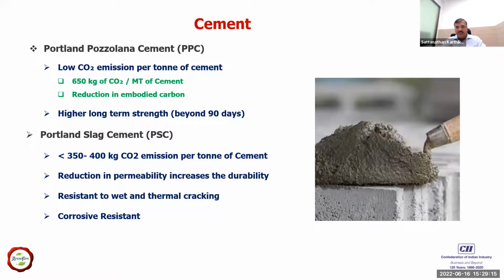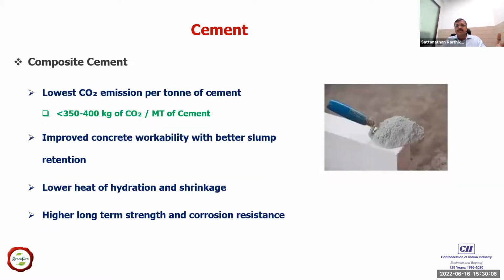Very similarly, there are other options available. For Portland slag cement, the slag can be added to the extent of about 70% as per the BIS standard, so obviously the carbon footprint comes down even lower. Compared to OPC, there is an increase in durability, and it also addresses corrosion-related issues. Even in terms of thermal cracking, it is a much better cement compared to ordinary Portland cement. So apart from the reduction in carbon footprint, if you go for blended cement, there are many more benefits in terms of increase in strength, durability and corrosion resistance.